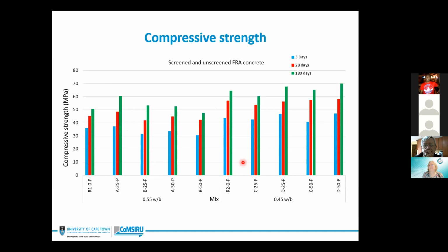The results of the compressive strength basically show that for our screened FRA concrete at 0.5, it can be seen that the strength decreases as FRA content increases. There's this general trend here. Of course, this can be attributed to the different replacement levels of FRA. So this can be attributed to the adhered cement paste that is present in the FRA matrix.